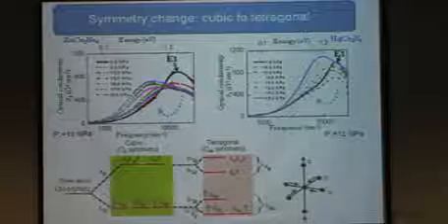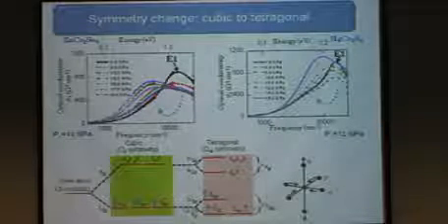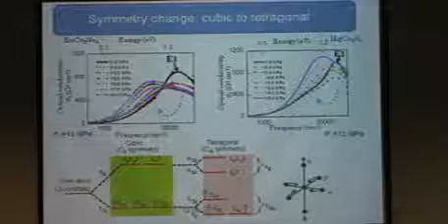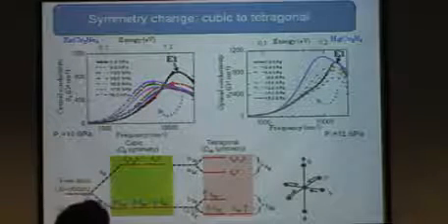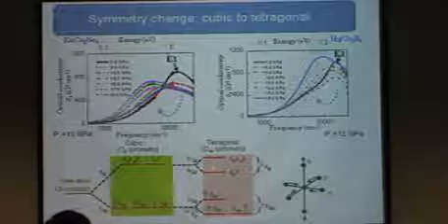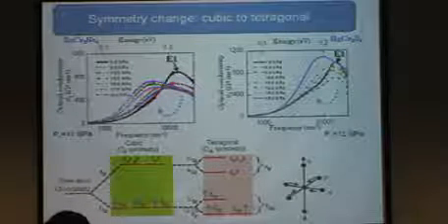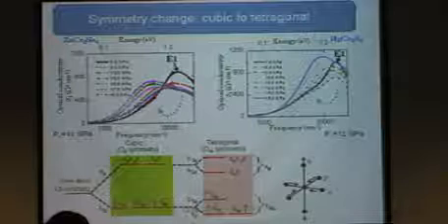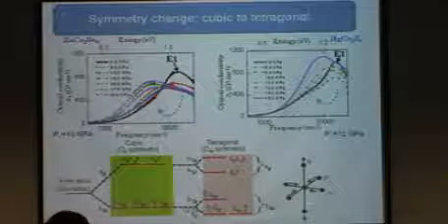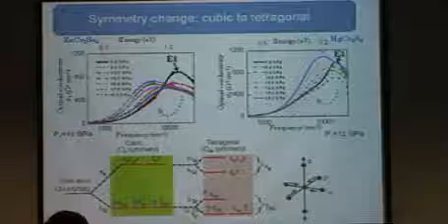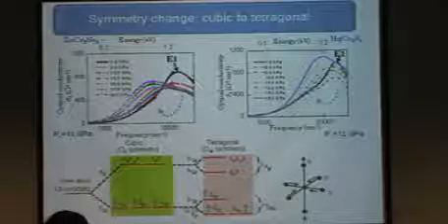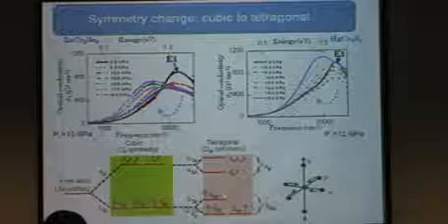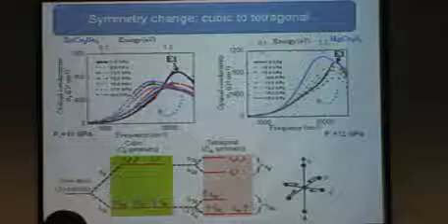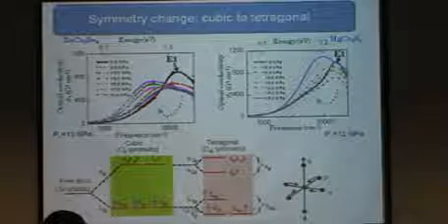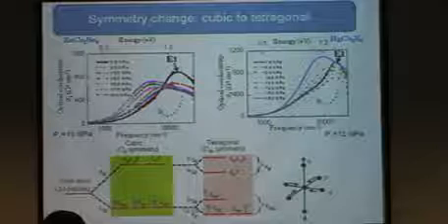And in this way, if you consider the initial state, and then you excite from this d level to another higher d level, then the energy used to excite this electron is lower compared to when it was at cubic symmetry. So that's how we interpret that the shifting of this band towards low frequency is because you reduce the splitting between two orbitals.